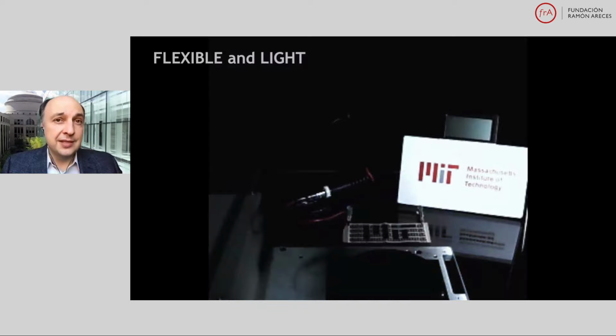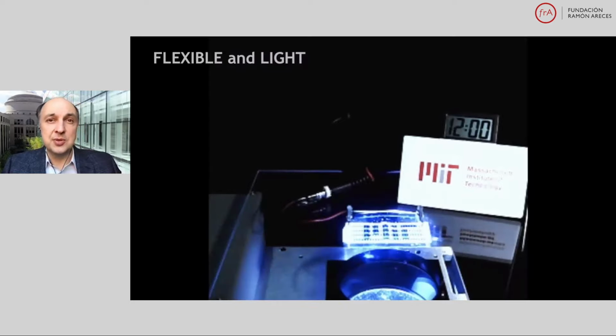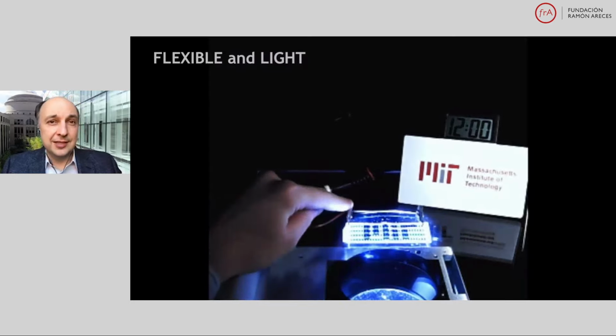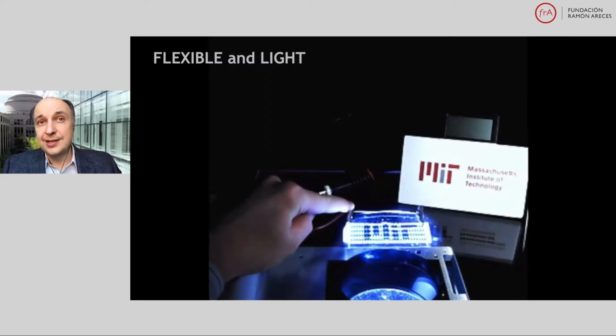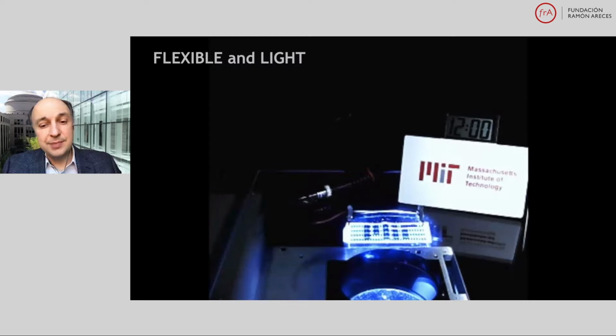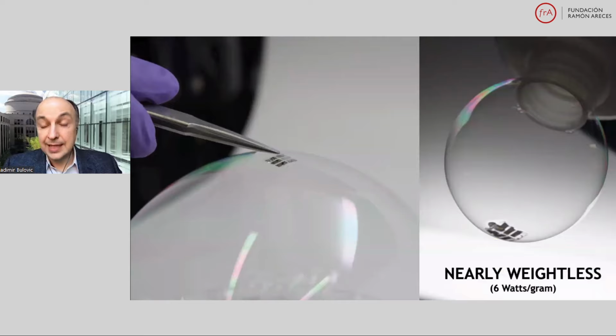They're so thin that mechanical stresses that they experience do not affect them. A typical cell like a silicon one would get cracked in the process of being rolled on the rollers of the laser printer. But these cells don't even notice that they're being bent. They're so thin that bending doesn't introduce any additional thin film stresses onto them. You can even remove the paper.